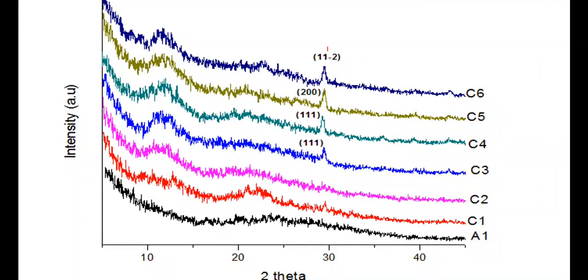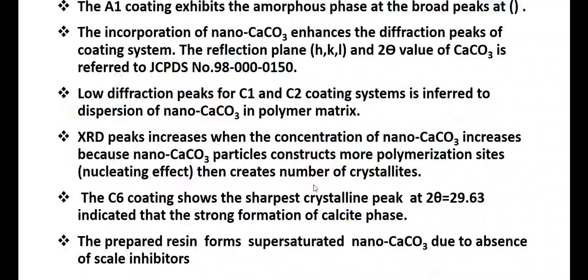We can see that when the nanocalcium carbonate increases, the morphology from amorphous becomes more crystalline, so the crystallinity increases. You can see at 111, 200 and 112 a sharp peak appearing. It shows that the crystallinity increases due to the nanocalcium carbonate incorporated into the binder system. So from here, we can say that the A1 coating system exhibits the amorphous phase with broad peaks, and the incorporation of nanocalcium carbonate enhances the diffraction peaks of the coating system, and the reflection of HKL and 2 theta value of calcium carbonate refers to our standard JCPDS number.